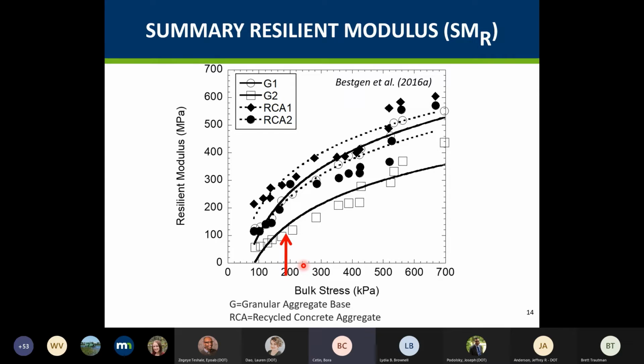And what the NCHRP 128, which is the most commonly used standard or report to determine the summary resilient modulus values, says is: if you're using a material as a pavement foundation, and you want to determine a summary resilient modulus value that can be used as an input in your pavement analysis, you pick the resilient modulus value that corresponds to 208 kilopascal of bulk stress. I apologize, this arrow shifted to the left a little bit. It should be here. The resilient modulus value that corresponds to 208 kilopascal bulk stress is what you can use as an input in your pavement ME analysis as a resilient modulus value that represents that particular material when it is used in pavement foundation systems.